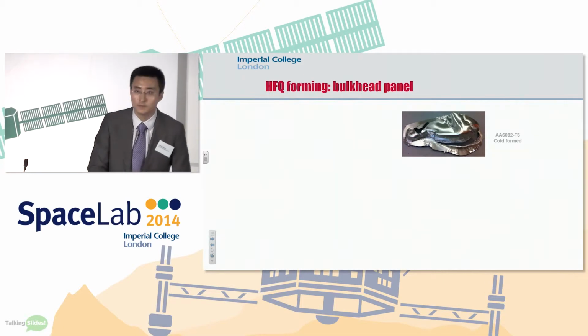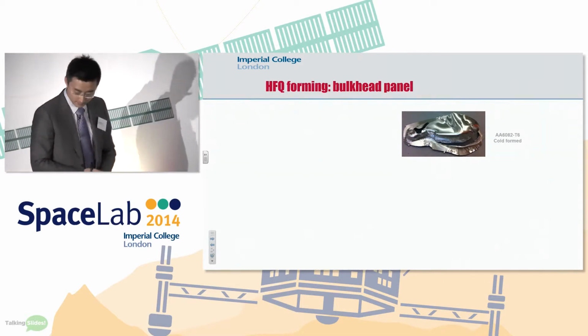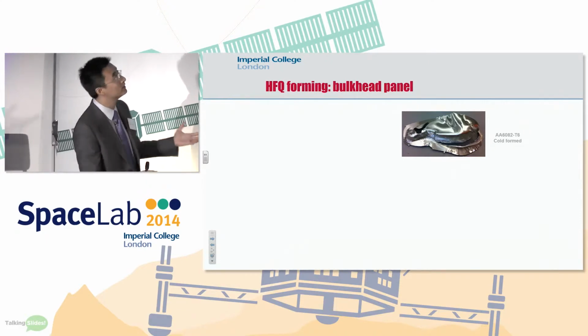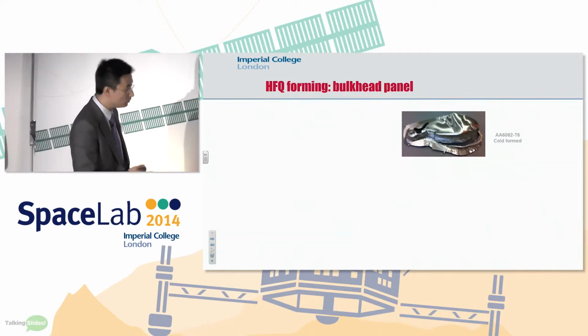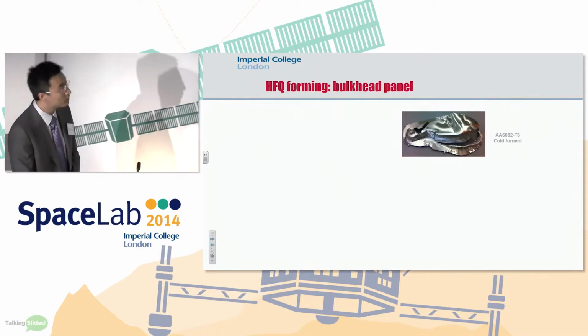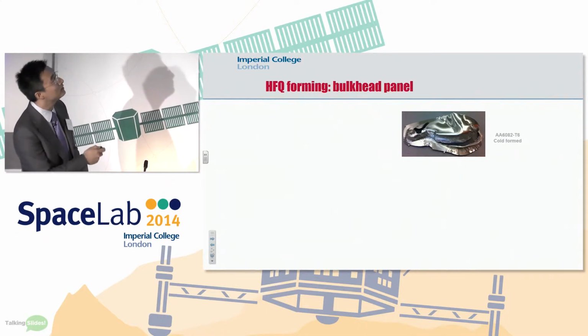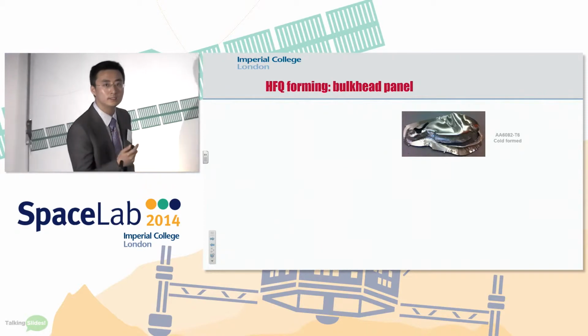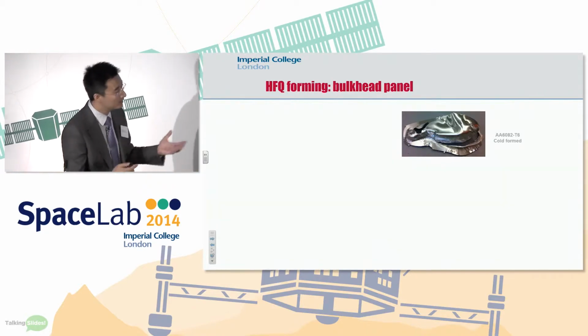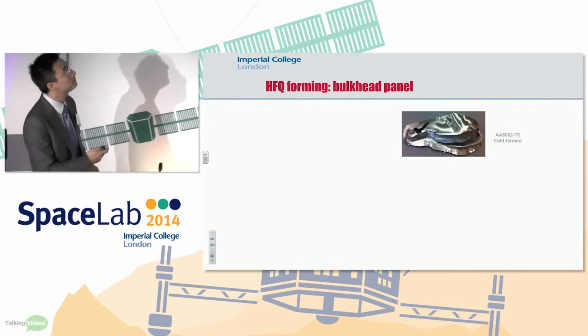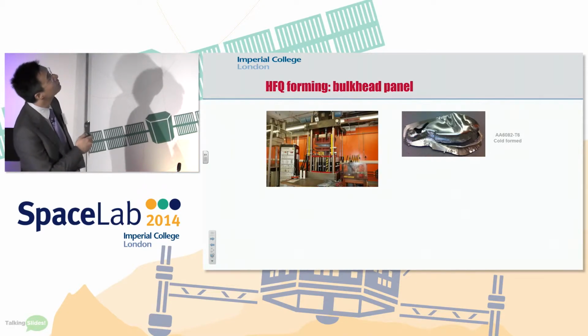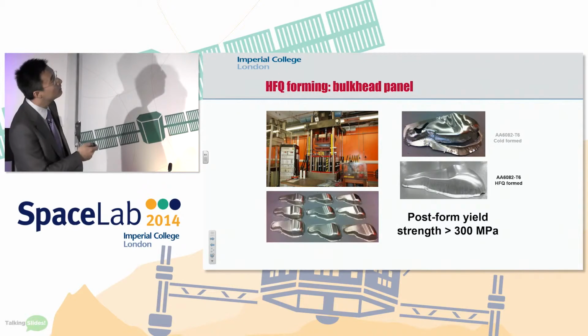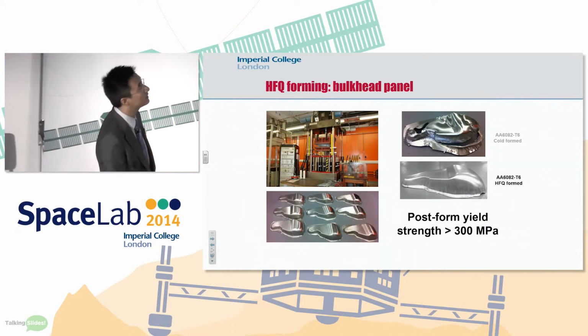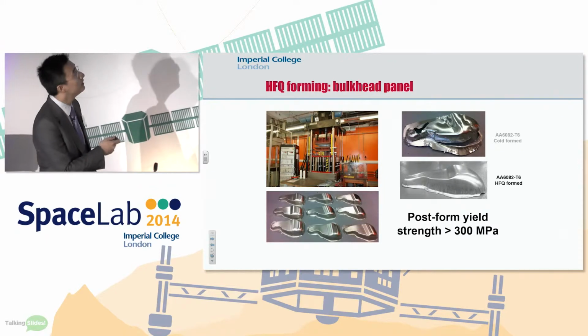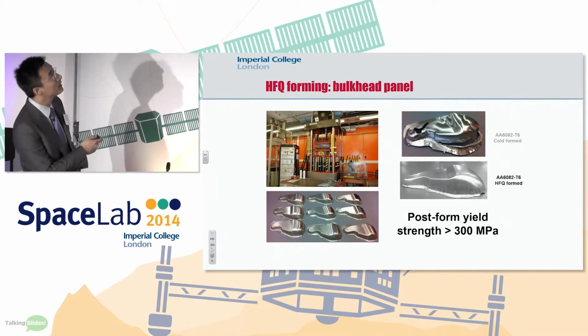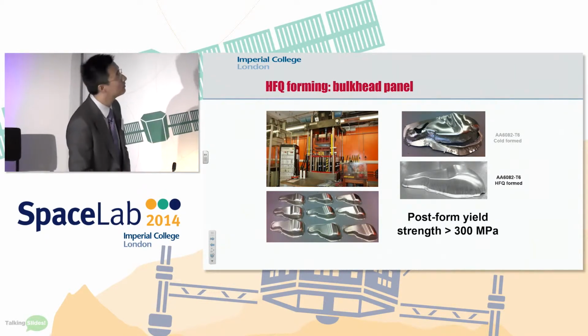We have another customer, the other day came to us and asking us if we can use 6000 series to form a very complicated shape, real components. And they provide us the die, and we tried by using their original material, which is in T6 condition. This is the maximum strength of this material. And we developed our own tool in our lab, and we formed by using HFQ technology very successfully again. So the part is very complicated in shape. At room temperature, we can't form the part at all.